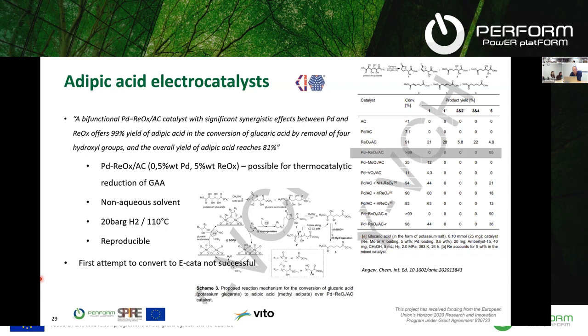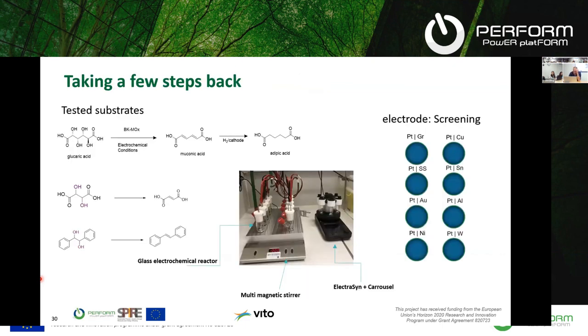First attempts to also use these kinds of catalysts in an electrocatalytic way were not successful. So then we took a few steps back and tested a few substrates which were similar to glucaric acid, and tried different types of electrocatalysts in these very small cells. So as you can see, the scale has to come down again due to the fact that we did not have any good solution yet for the electrocatalytic conversion. We did a lot of screenings with different electrodes and metal oxides in specific electrochemical conditions.